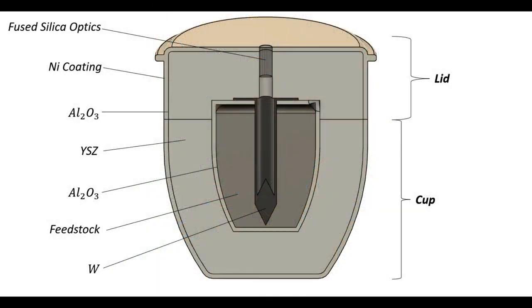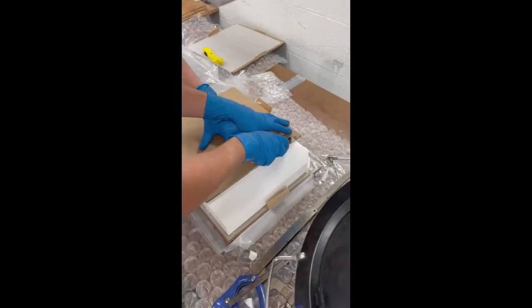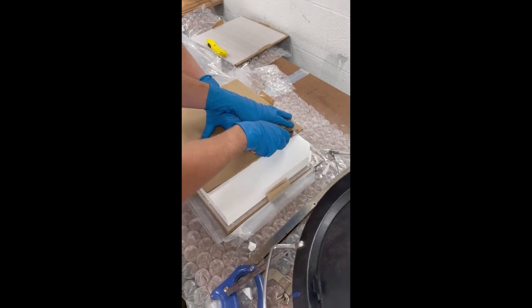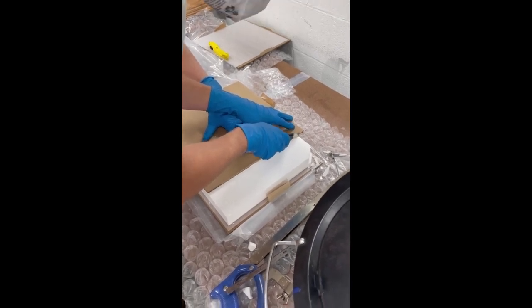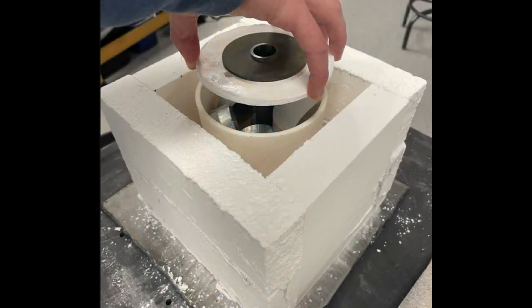The solar concentrator system carries rays directly into an insulated crucible to ensure that heat can be sufficiently accumulated to reach target casting temperatures. To validate the insulative performance of the crucible design, the team fabricated a prototype crucible for thermal cycling tests in a box furnace, which closely controlled the external temperature while a thermocouple on the inside of the crucible logged the temperature of liquefying aluminum feedstock.